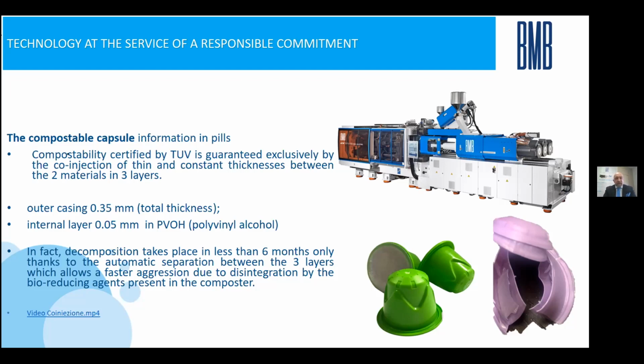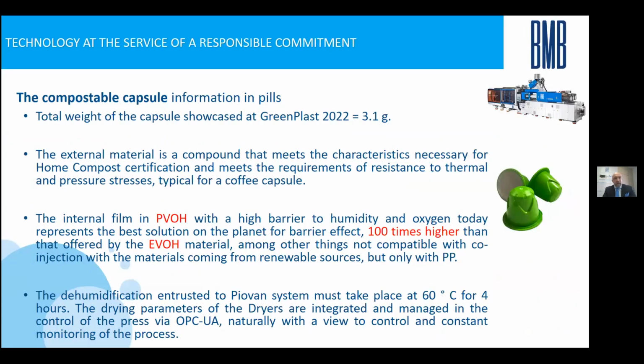PVOH is the barrier of oxygen and humidity. Its thickness is 0.05, and the total thickness of the caps is only 0.35 millimeter. You can imagine, 3.1 grams is the total weight of the caps. PVOH is a new material for the barrier to the oxygen, and came after EVOH, and is 100 times better.